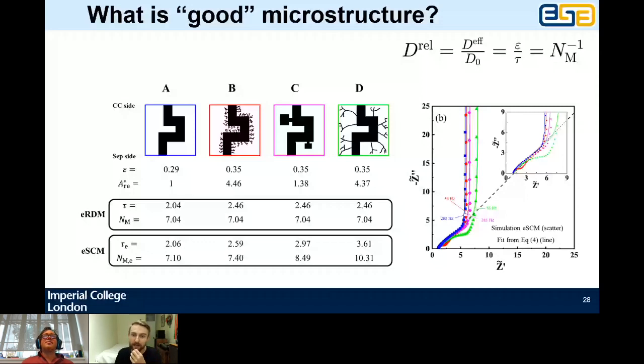Thank you for your talk. Is it possible for the tortuosity factor to be less than 1? So conventional tortuosity factor, no, it's defined between 1 and infinity. The electrode tortuosity factor can be from 0 to infinity in principle, i.e. it's thinking about how does your system compare to a straight pipe if you wanted to get into the walls of the pipe and not out the other end of the pipe. And of course, you can do much better than a straight pipe for that.